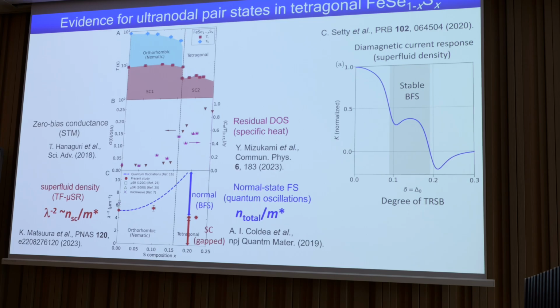Recent calculations of this Bogoliubov Fermi surface show that if you change the degree of time reversal symmetry breaking, you can find a parameter range in which this Bogoliubov Fermi surface can be stable, which is the shaded area. In this area, the superfluid density should be strongly suppressed from the original value. This seems to be consistent with what we observed in our data.